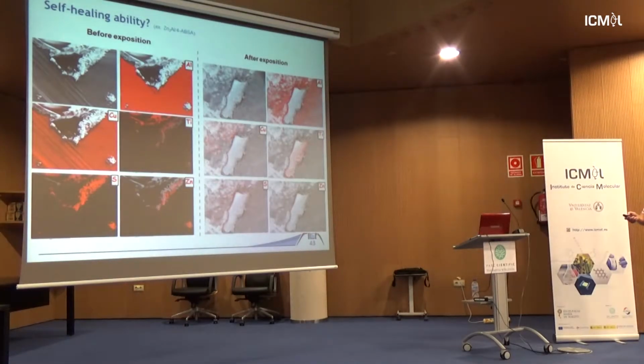And of course, we perform some microscope analysis before and after scratch, and before and after immersion in salty water. So you can see on the scratch zinc and sulfur coming from the amino acid cysteine, and zinc coming from the LDH. Aluminum, of course, is not the best element to probe, because it's an aluminum substrate. Copper, so it's an aluminum copper alloy, and you have some titanium present because it's in the polymer coating. So that's before immersion, so that you have the LDH, the zinc amino organo inorganic LDH, at the scratch level, just at the frontier.